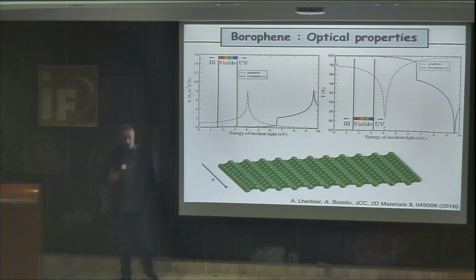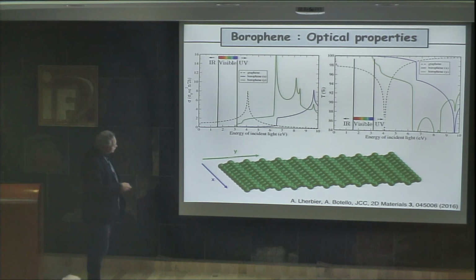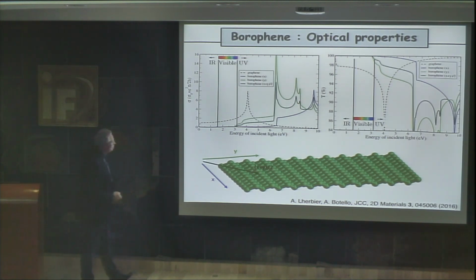So what about Borophene? Can we predict something about the optical properties of this system? We start with incident light polarized along the x-axis. Since the material is anisotropic, we really have to check if there are differences between the x and y axes for the polarization of the light. This is the blue curve, compared again to graphene, which is still here. You see there is nearly no optical conductivity in the visible range. If we look at the polarization along y, it's clearly anisotropic in the UV, so you have a completely different response in this case. Since you never know experimentally if you will be in the y or x direction, mostly you will get an average of these two, which is this black curve.